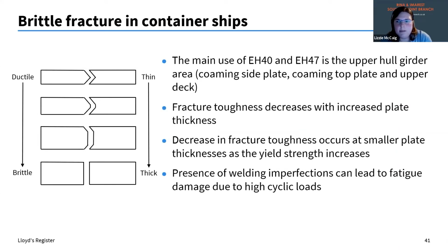The other problem is that as a material gets thicker, it is more likely to experience brittle fracture rather than ductile fracture. And also, as the strength of the steel increases, you're more likely to see brittle fracture versus ductile fracture. So if you have both an increase in the yield strength of the steel and an increase in the thickness of the steel, then you're increasing even more the possibility that you could experience brittle fracture. That, combined with the presence of welding imperfections, which could lead to fatigue damage because you've also got high cyclic loads, means this is a particular issue for container ships.